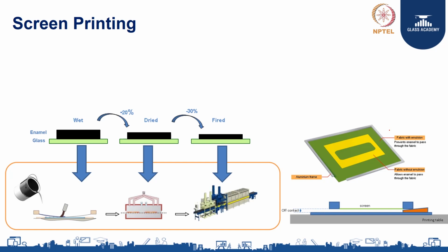Basically, the firing is the tempering process. Once you do that, the coating is fused on the glass surface. Thereby you cannot remove it. Basically, the coating is deposited, which means fused on the glass. So it's a permanent bonding between the glass and the coating, which screen printing helps achieve. You can do any dots, stripes, based on the design of your silk screen, you can get the patterns.